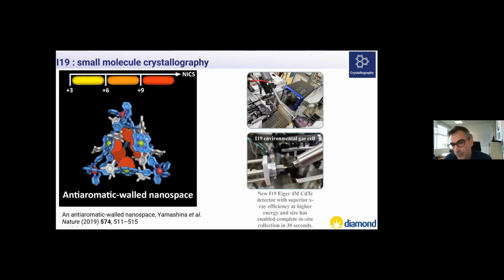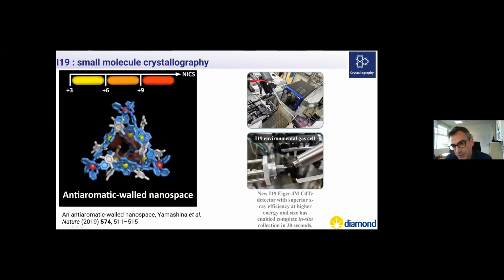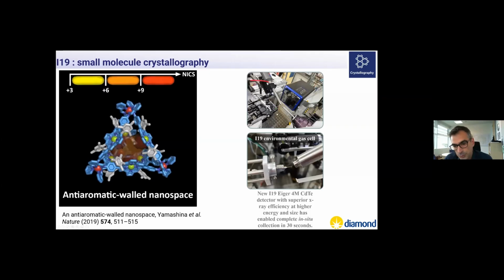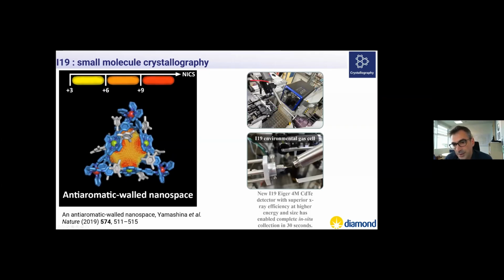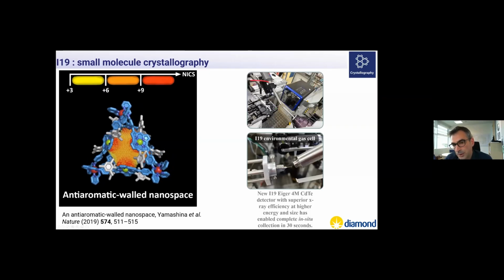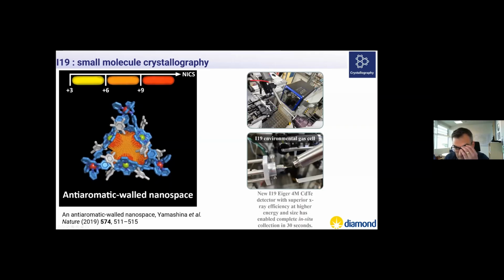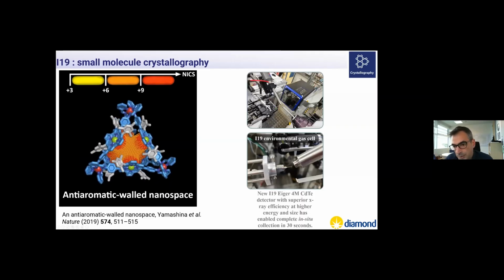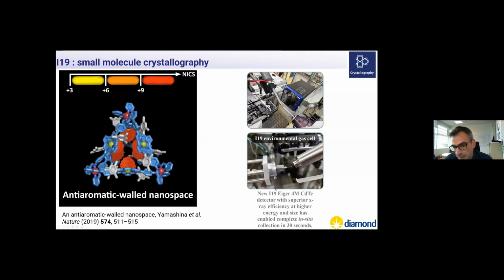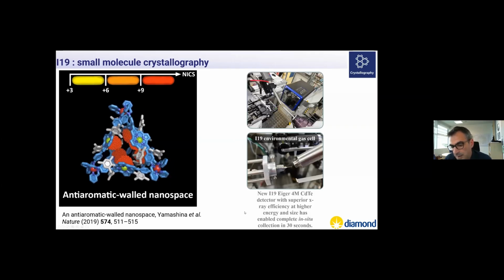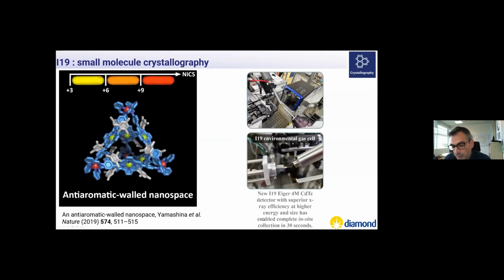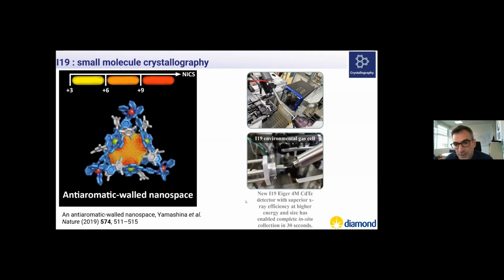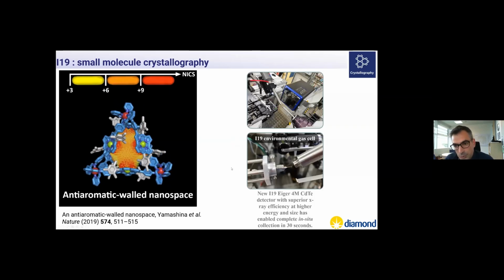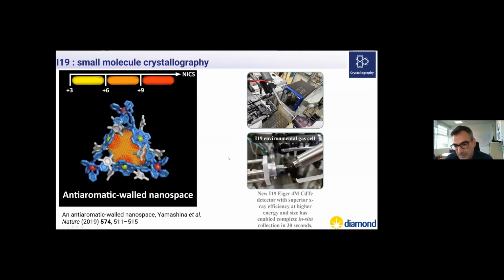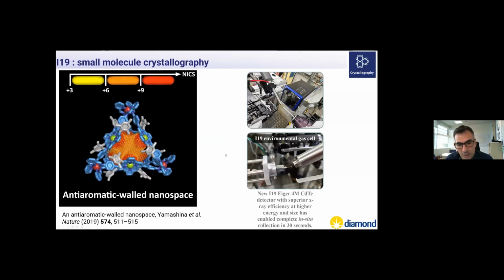We are really pushing the technology. We are pushing the technique in order to be able to do faster and faster measurements, in particular by implementing new detectors, for example, cadmium telluride detectors, on these beamlines, and we've recently achieved data collection times typically below 30 seconds for a full single crystal diffraction, and that now enables us to look at extremely fast systems in, for example, a gas environment or non-ambient conditions.